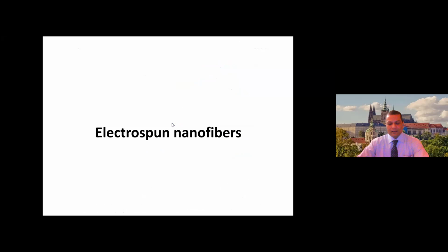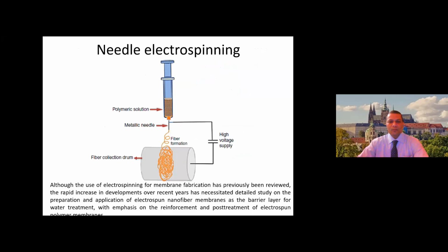One of the major structures in nanoscale is known as nanofibers, where the dimensions, especially the diameter, are in a few nanometers. As per the classification of nanomaterials, the diameter should be less than 100 nanometers. The technique used to produce nanofibers is called electrospinning. It is not by melt spinning or solution spinning. It is by use of an electrostatic field, and we need a very strong electrostatic field of the order of 10,000 volts between the nozzle or the generation point and the substrate or the collection point.